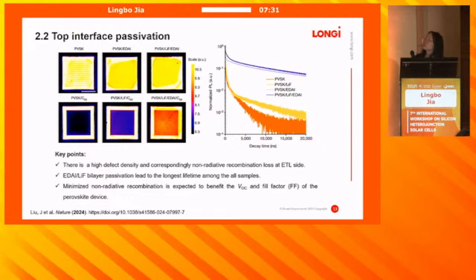So in order to address this issue, we introduced an EDAI and lithium fluoride bilayer to passivate the defects between this interface. We can also notice that after we incorporate this bifunctional layer, the PL mapping intensity and also the lifetime of perovskite films is enhanced. So we think by using these strategies, we can minimize the non-radiative recombination at this interface.